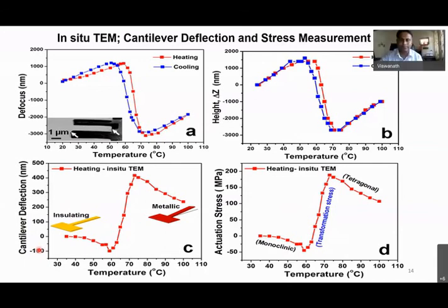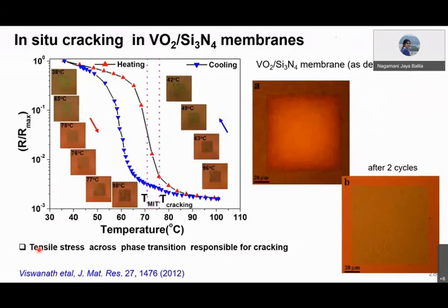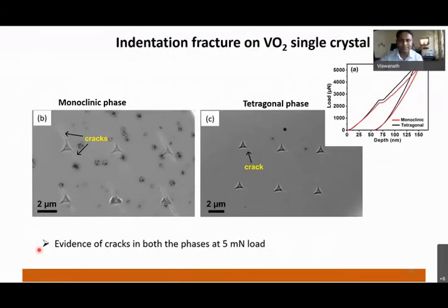Maybe one more point on this indentation fracture toughness that you are looking at. The cracking pattern is, of course, expected to be highly anisotropic. You see it always aligned along certain directions and not others. Does it correspond to the cleavage facets? I guess that's also a reason why we get some differences, since these formulas usually apply to homogeneous specimens. For single crystals, some more approximations are done. However, I think this is a very good tool to measure. I'm also interested in measuring these kinds of things. We were trying to do it with freestanding structures to eliminate the stress effect. So it was very good to see it being measured with the nanoindentation tool itself.